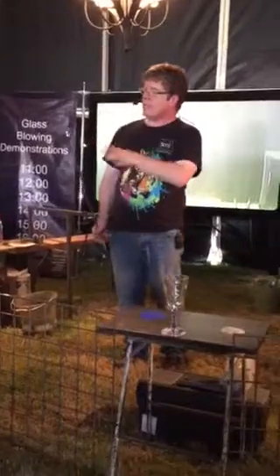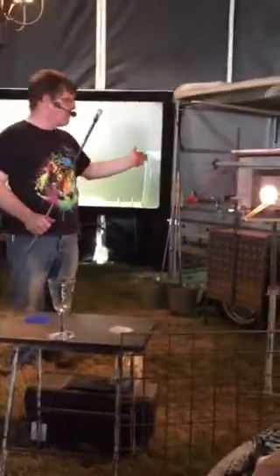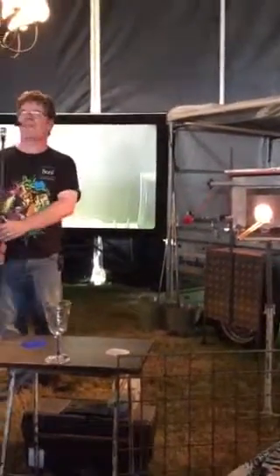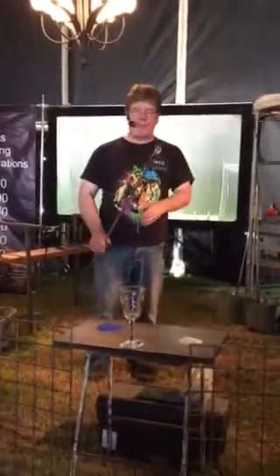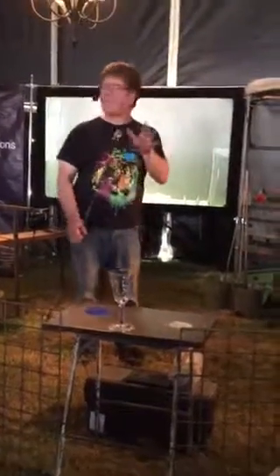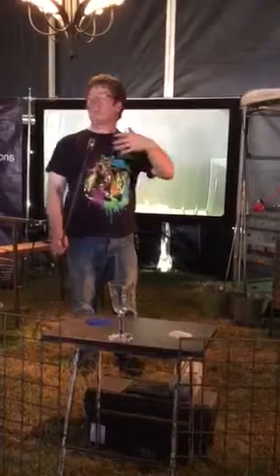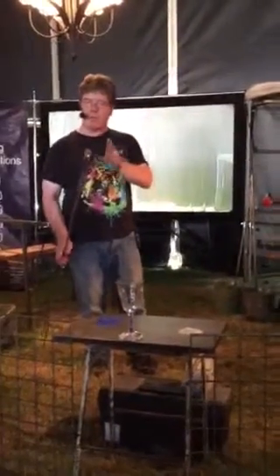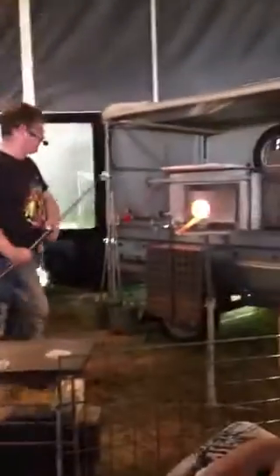And if I let it cool down to 600 degrees, I've got a bit more time before the glass starts to move with all that heat inside the furnace. And you get to know all the different temperatures from the colour of the glass, and 600 degrees is the first point where there's no extra colour in it. The first point has gone back to being clear. So we're at 600 degrees now.